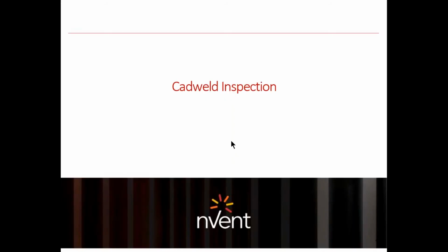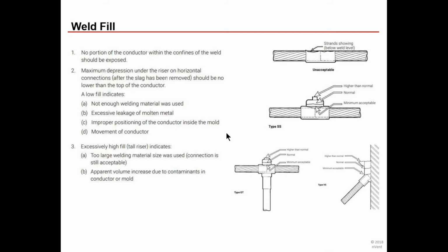Okay. So once you've made the weld, you want to inspect it. Here are some things you need to look out for when doing an inspection. First off, if at any point you see conductor coming out of where the weld should be, so the weld did not form properly, and you can actually see conductor where the top of the weld was too thin or wasn't even formed, that is an unacceptable weld.